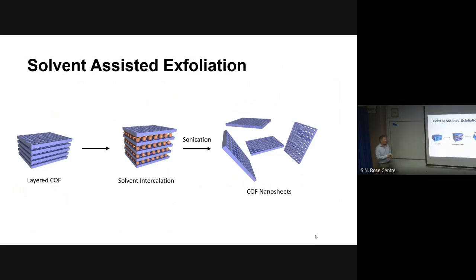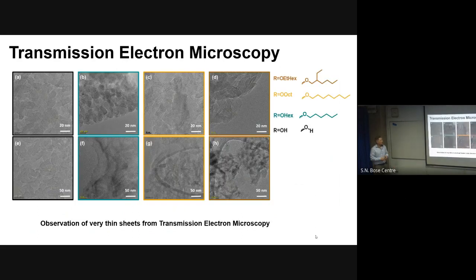So this is our exfoliation strategy. We soak the materials in the solvent. We hope that the side chains help in catching the layers. Then we sonicate them, and have the curved nanosheets inside the solution. Here we can see the ethyl acetate exfoliated materials. For the non-functionalized material, the resulting flakes are very large and very thick. If we have the longer side chains, the sheets are a bit smaller in size, but the contrast is also much lower, so they are most likely much thinner. This is the first observation that this approach really works.